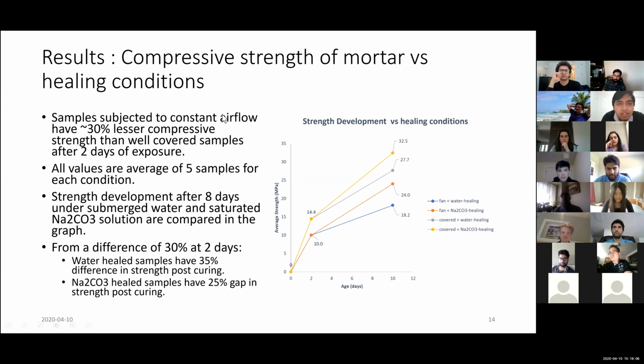So this is a compressive strength of mortar. And so here in this graph, we can see all of that data. First of all, we have two branches. One has been covered all the time, and the other branch has been subjected to evaporation through the first 2 days. And in the first 2 days, we can see that there is a decrease in strength if we leave the samples under a constant flow of air. This is an average of 5 samples each on both, and this difference was roughly 30%. So there is a 30% loss in strength if we don't cover our samples and leave them under a constant flow of air. So this difference is present at 2 days.